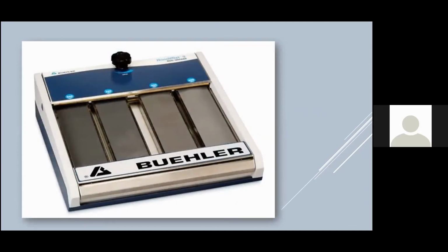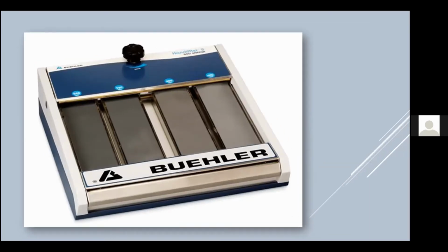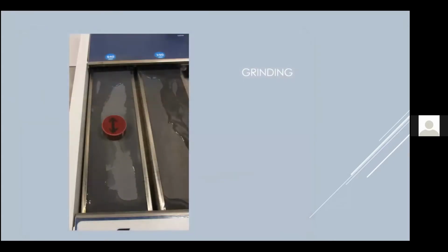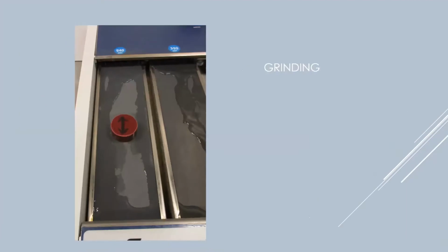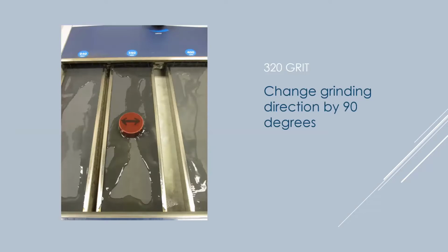This is how I do it in the lab. It's called a Buehler HandyMet, and it has rolls of silicon carbide paper going from left to right of different grit size. We do the same thing in the field too. All I do is put these mounted samples and go back and forth. There's some water there to remove the grinding particles. And then when I go to the finer grit size, I rotate it 90 degrees. The reason I'm rotating it 90 degrees is that I'm trying to ensure that I removed all the scratches from the previous step. And we do the same thing in the field.